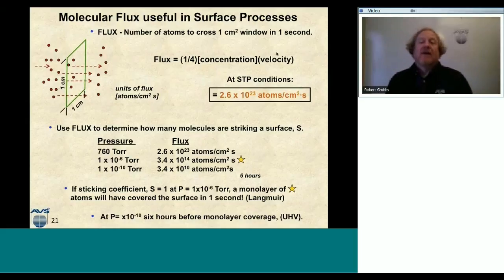So flux can be simply calculated by taking the concentration, which is pressure, multiplying it by the average velocity that we've gotten from our Maxwell speed distribution, and dividing by 4. The unit of flux is the number of atoms or molecules per centimeter squared per second. At STP conditions, standard temperature and pressure, we get about 10 to the 23rd atoms going through 1 centimeter squared in 1 second.